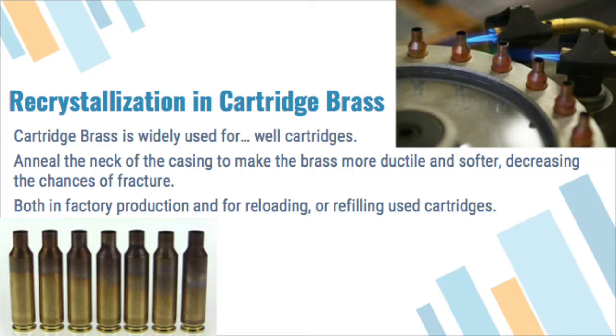Annealing of cartridge brass is extremely important for ammunition. To produce the shape of a casing, the metal must be bent into shape. This work hardens the brass at the neck of the casing. The neck is annealed to be more malleable, so when firing it assists the bullet chamber and can assist with expansion as the bullet is fired.